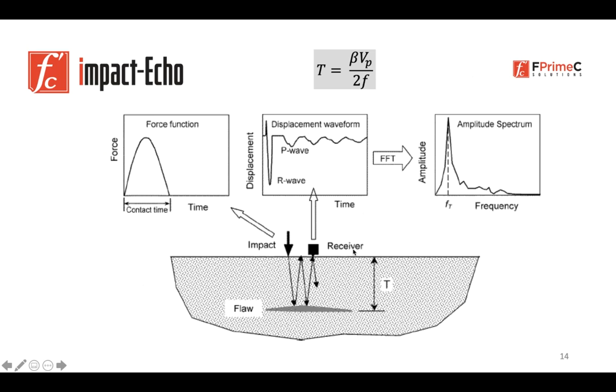So eventually we can measure the thickness, or we can find the location of the internal defects and flaws. The other parameter, which is called beta, is the geometry factor. In most cases, in plate-shaped structural members, that beta number is equal to 0.96. And if you want to know how you can calculate that beta number based on the geometry of